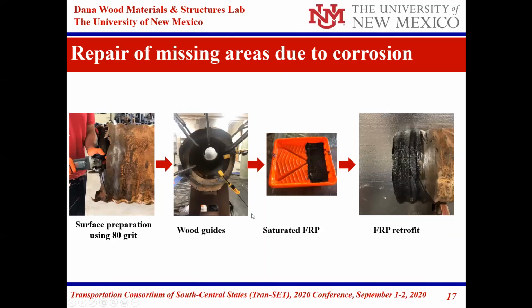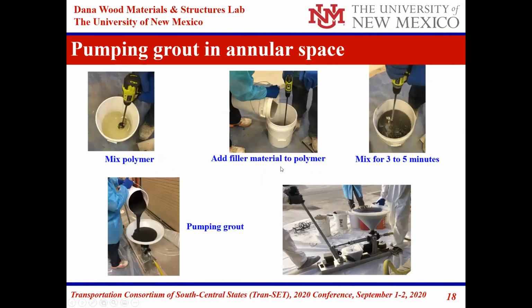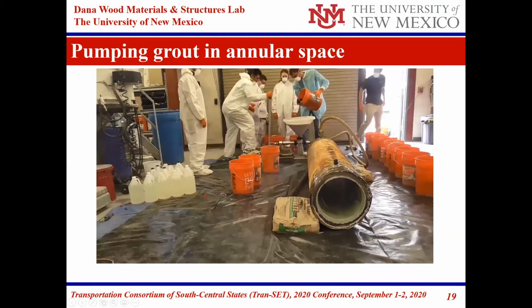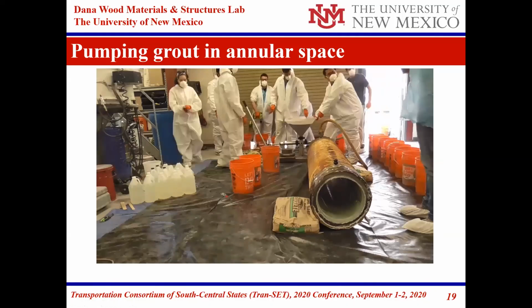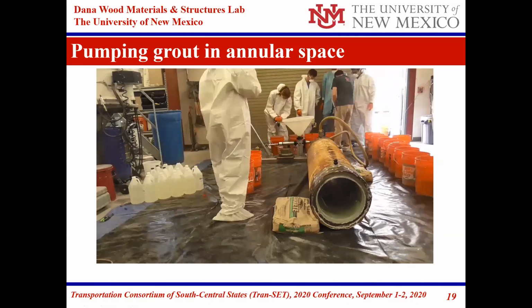Then we basically mix our grout, filling the material into the polymer. Grout is mixed for about 3-5 minutes. And then the grout is pumped here to the hand pump, and you can see that here, this is the corrugated pipe. You see the students doing the work, filling the pump with the grout.